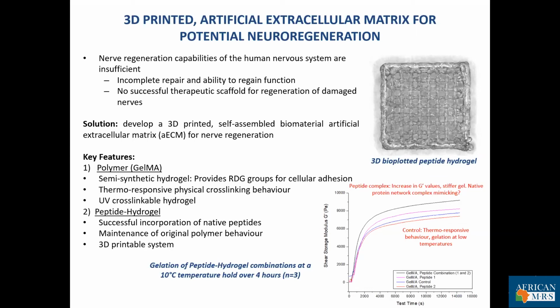So what was proposed here was a 3D printed self-assembled biomaterial extracellular matrix for nerve regeneration, combining a polymer which is thermoresponsive and UV cross-linkable with a peptide to create a peptide hydrogel. And this was also a 3D printable system. So basically, we were creating an enhanced extracellular matrix structure to promote the adhesion of your neural cells, promoting neural regeneration.